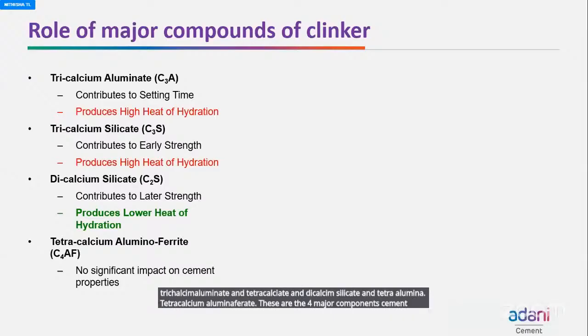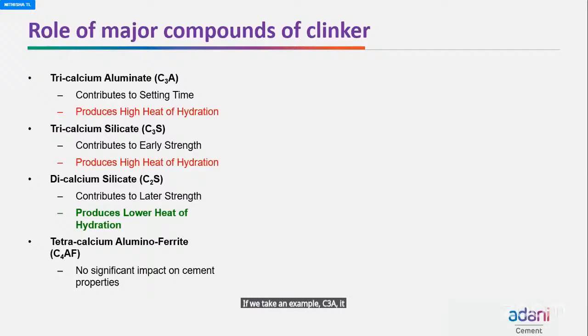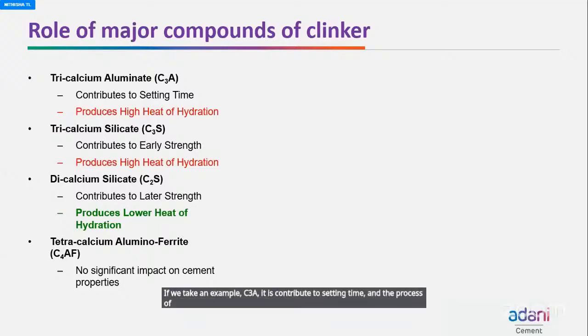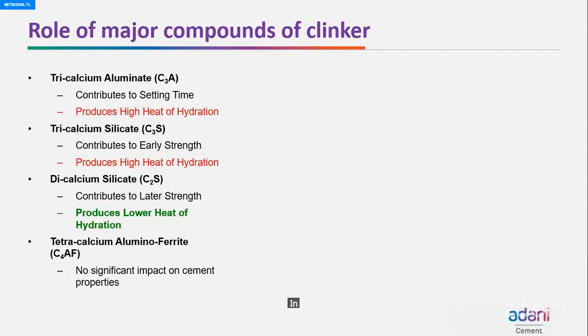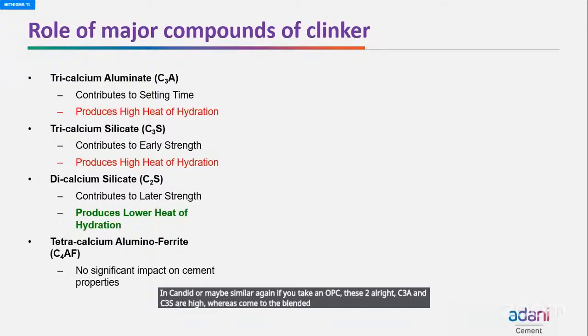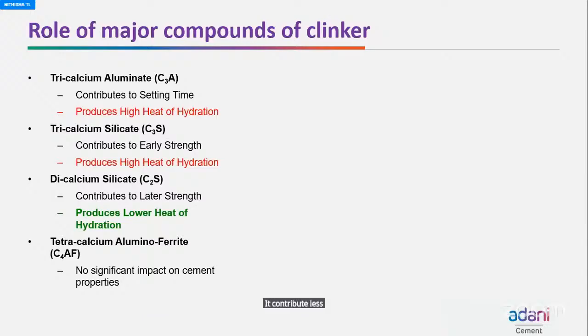If you take an example, C3A contributes to setting time and a high heat of hydration. This is a major disadvantage of too much C3A. And C3S contributes early strength and also more heat. Wherever there is a red flag mark, it is a danger in concrete or cement. If you take OPC, these two, C3A and C3S, are high, whereas in blended cement, C2S is more compared to OPC. So that is the reason you get more durability in blended cement compared to OPC. It contributes less initial strength and produces a low heat of hydration. It will give you the highest strength at later stage.